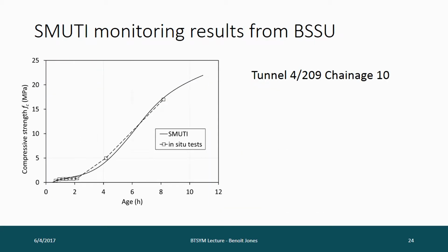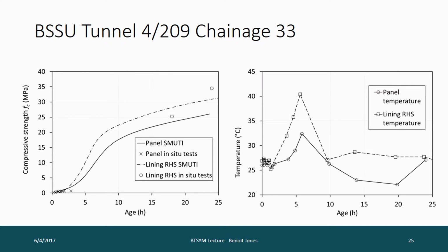So here's some typical results. Got some, and there's some in situ tests there as well. And here's some more. In this case, on the left is the strength versus age, and the X's are the penetrometer results in the panel, but then the circles later on are actual Hilti pull-out tests in the lining. And then we've got the smooth line is SMUTI on the panel, and the dashed-dot line is SMUTI on the lining.